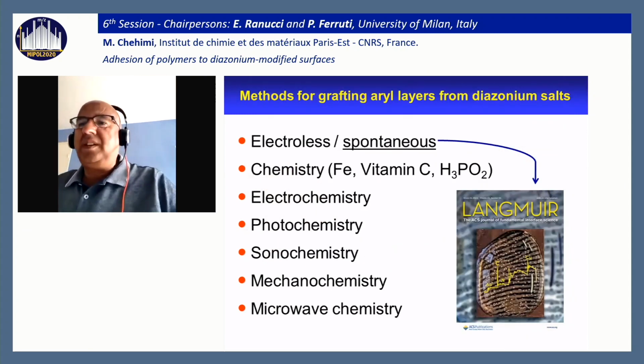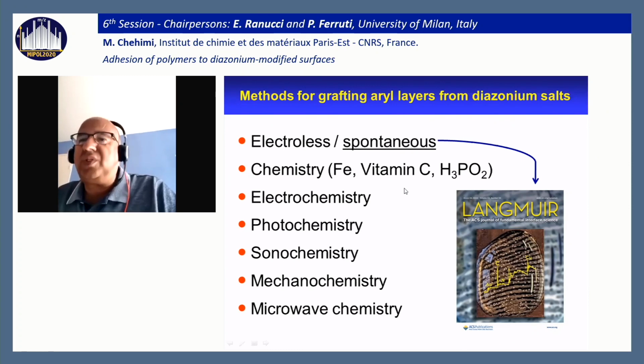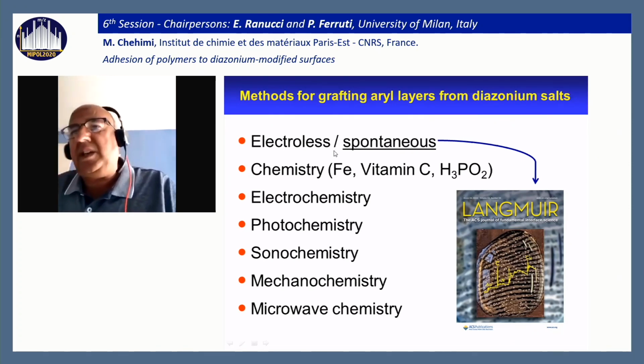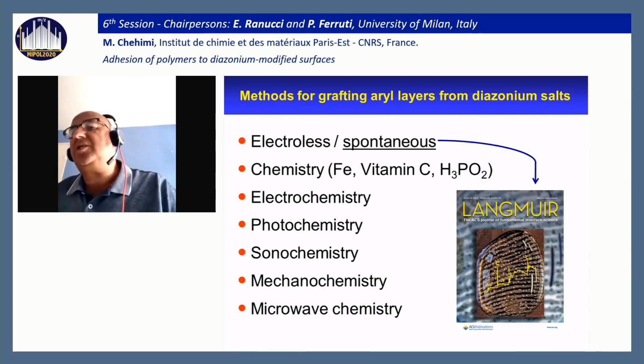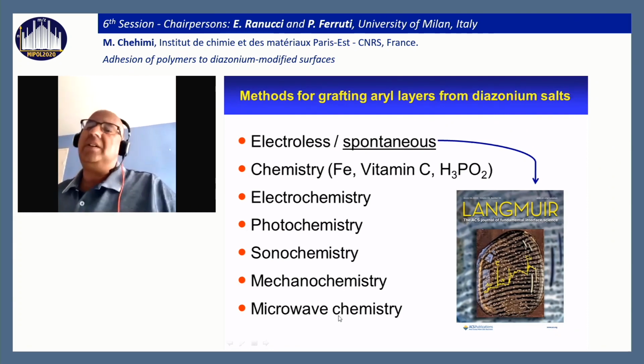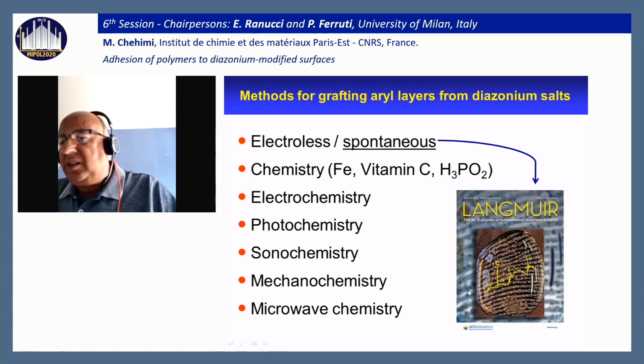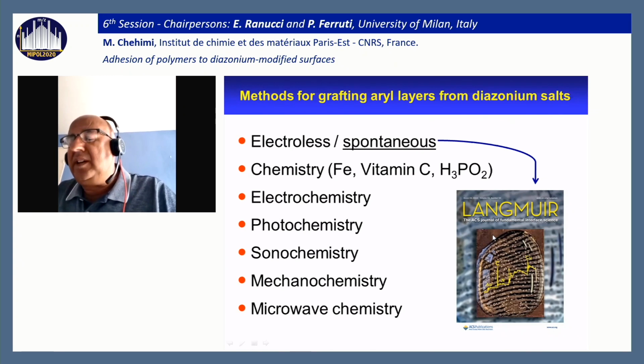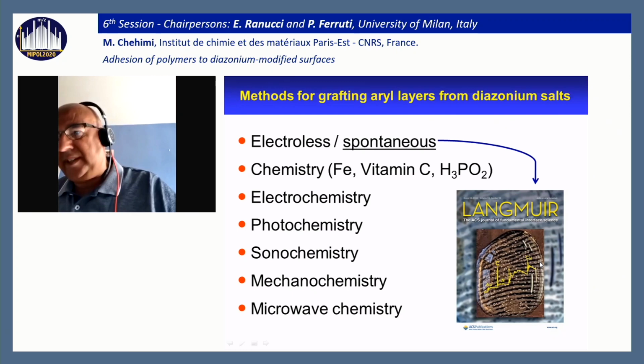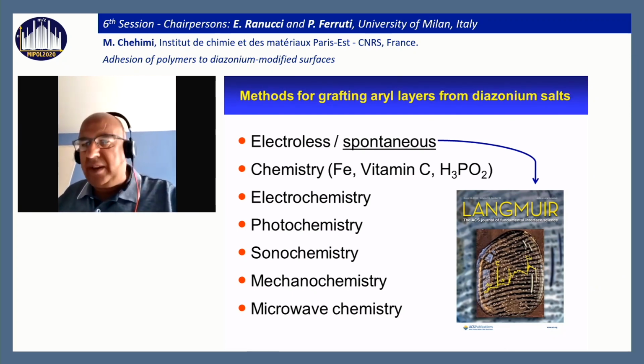So to make the reaction at the surface, we can use, of course, the spontaneous reaction if the surface has sufficient reducing power towards the diazonium salts. Also, we can use other reducing agents like iron powder or vitamin C, by electrochemistry, photochemistry, and many other processes. Spontaneously on copper, for example, we have demonstrated that diazonium gold tetrachloroaurate reacts with the surface of copper to permit the visualization of latent fingerprints on copper. This is for forensic science. This has been published recently in early 2020 in Langmuir.